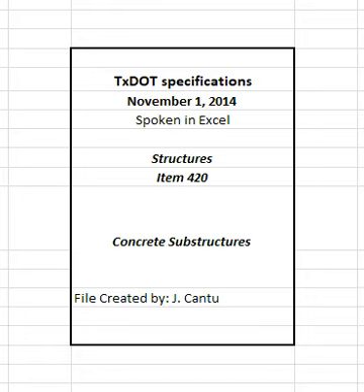Maintain the temperature at all surfaces of concrete in bents, piers, culvert walls, retaining walls, parapets, wing walls, top slabs of non-direct traffic culverts, and other similar formed concrete at or above 40 degrees Fahrenheit for 72 hours from the time of placement. Maintain the temperature of all other concrete, including the bottom slabs and footings of culverts, placed on or in the ground above 32 degrees Fahrenheit for 72 hours from the time of placement.